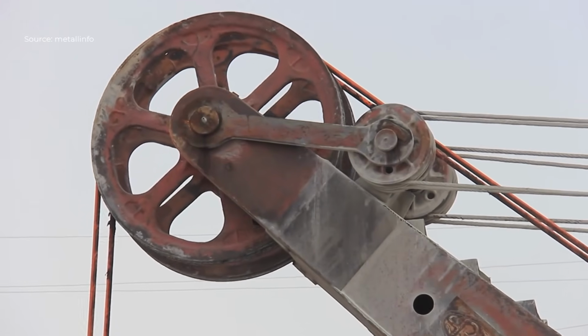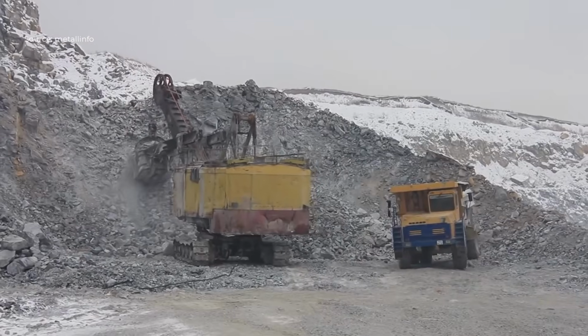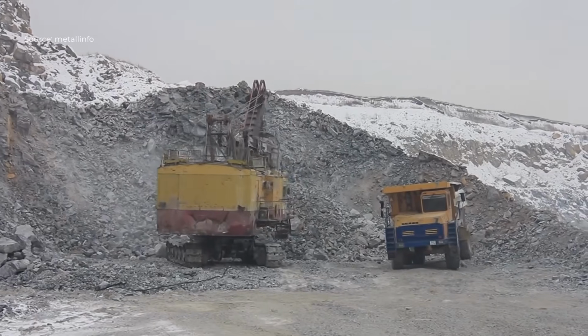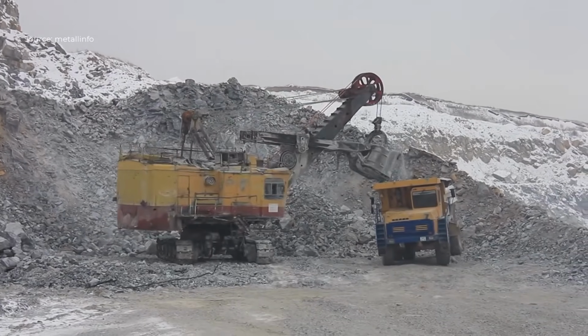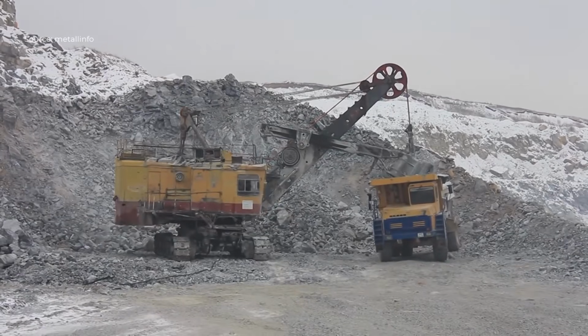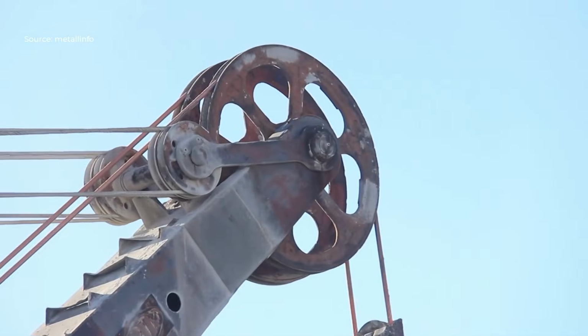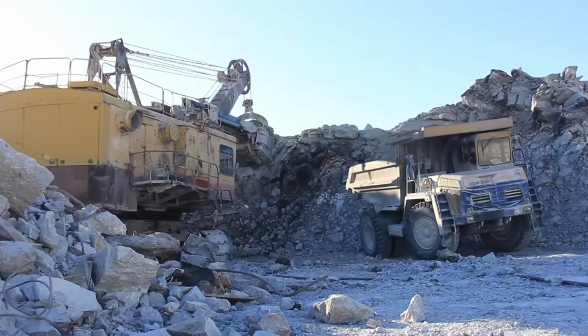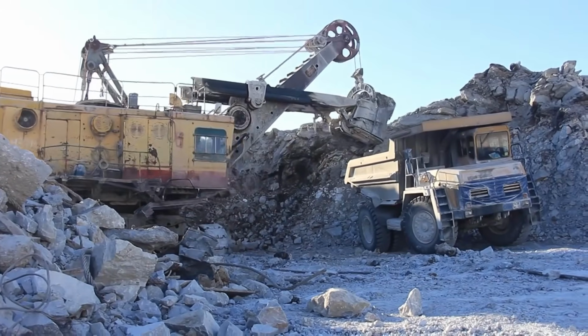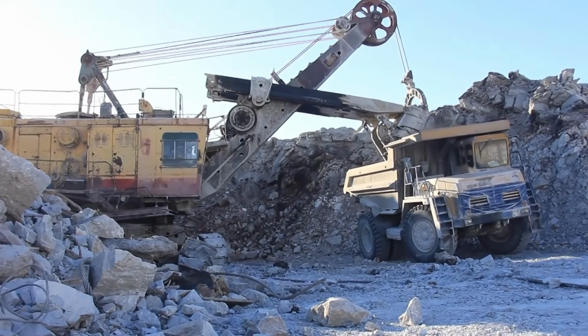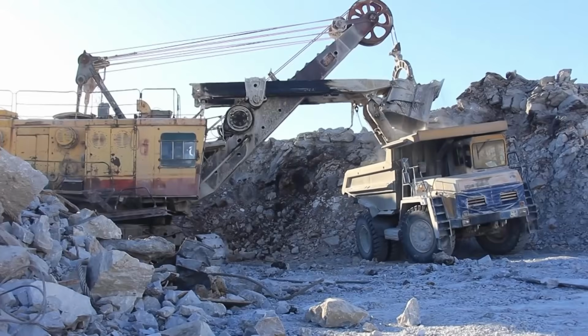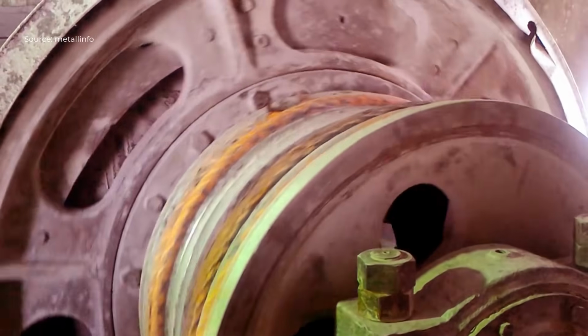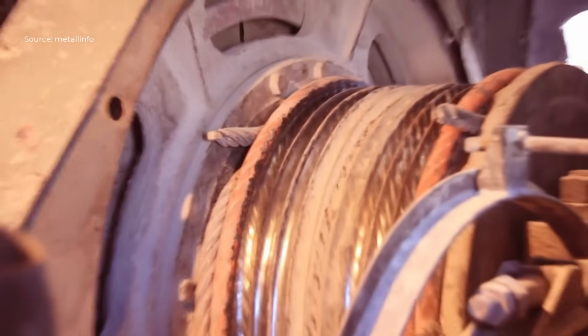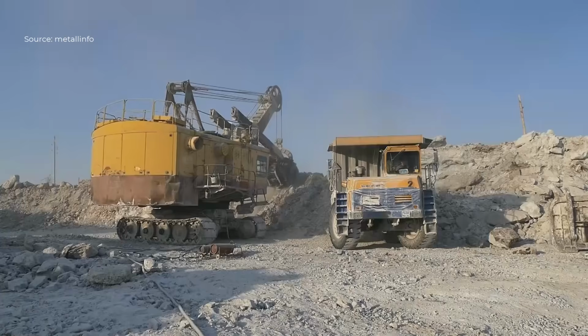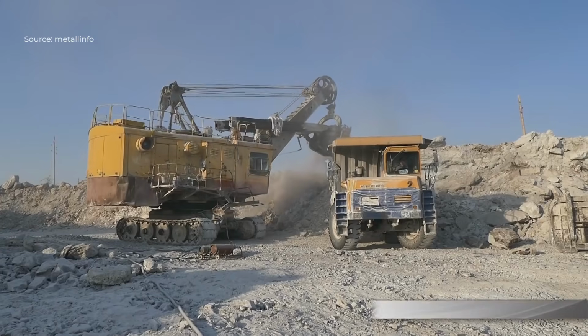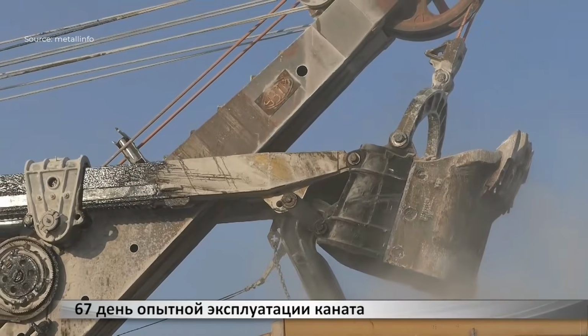To validate these advantages, BMK conducted extensive field tests. A 39 mm, 45.5 mm, 52 mm, and 57 mm polymer-coated ropes have already undergone industrial trials. Special attention was given to a 39 mm rope installed on an EKG-5 excavator at a limestone quarry. Weekly inspections were carried out over several months. The rope operated for more than 5 months in temperatures ranging from +5 degrees Celsius to -38 degrees Celsius, outperforming standard ropes without polymer coatings by approximately 1.5 months.